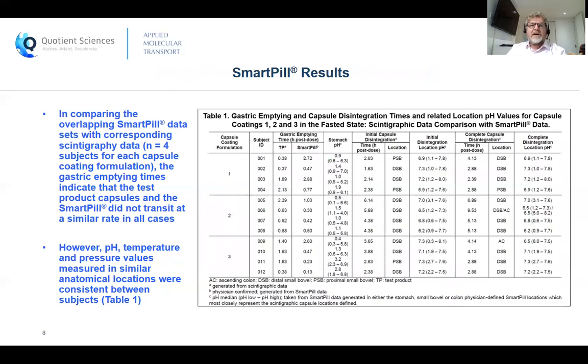Where smart pill data could be compared to scintigraphy results from the same dosing occasion, we've got the data here in table 1. The gastric emptying times indicated that the test products and the smart pill didn't transit at a similar rate in all cases, perhaps due to size and surface material differences. However, the pHs measured by the smart pill at the locations where initial capsule disintegration was identified by scintigraphy indicates that the coating systems were dissolving at pHs between 6 and 7, which was in line with expectations for the polymers we used.